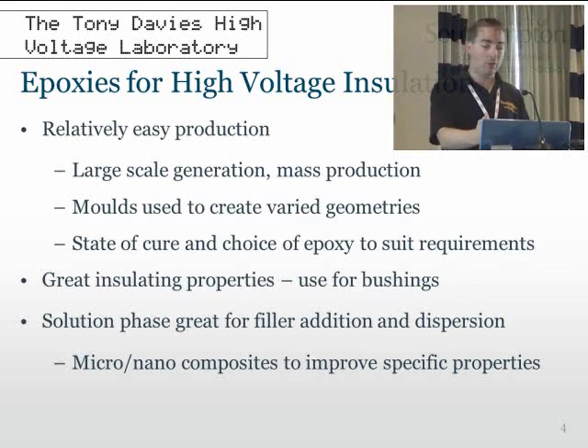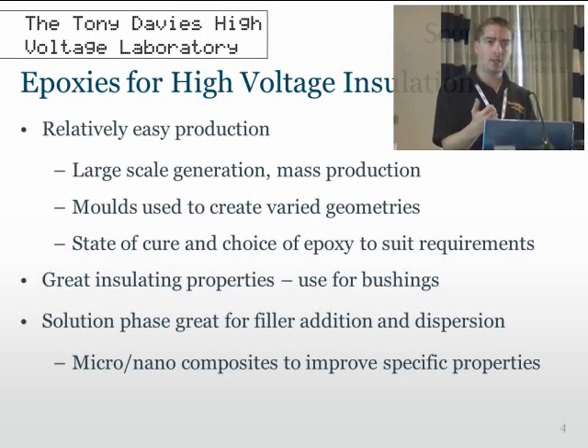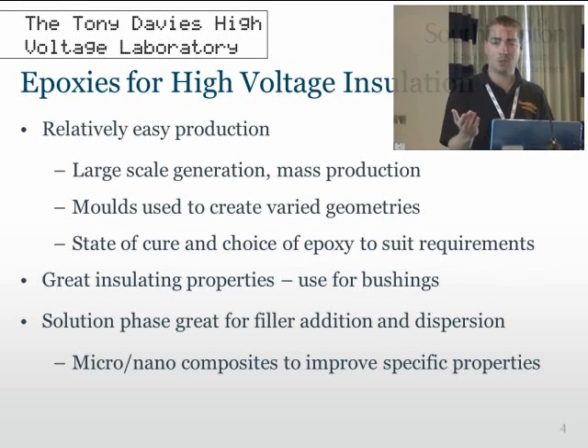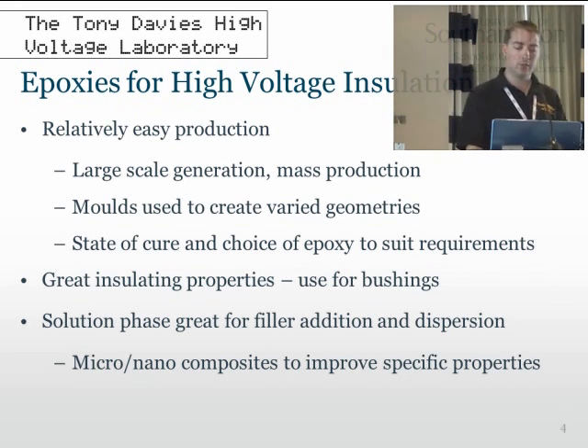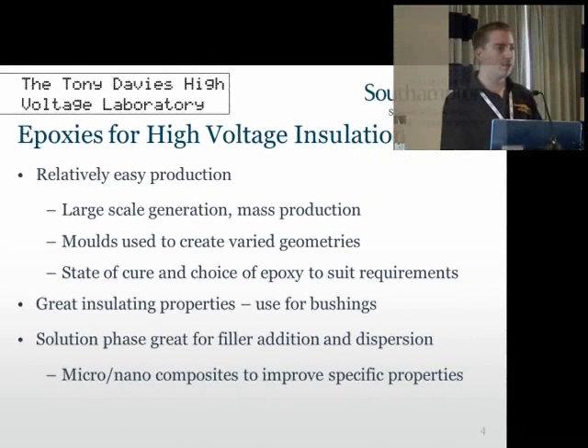For high voltage insulation, the best properties we're after are insulating and perhaps thermal conductivity. And also, one of the key points is that the solution phase that you go through while mixing the liquids is very suited to the addition of your micro and nano fillers. It's a lot easier to get these into solution than extruding into molten polymers.